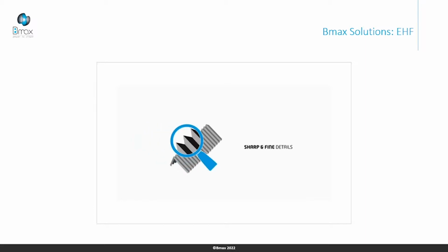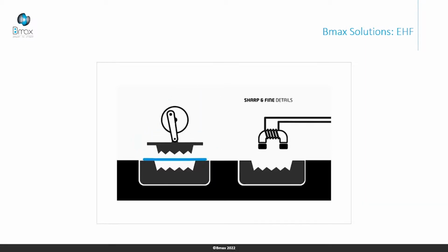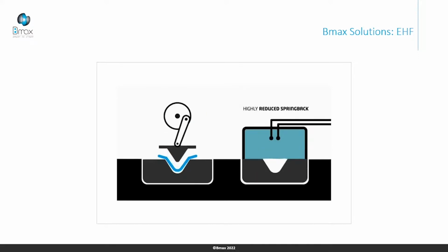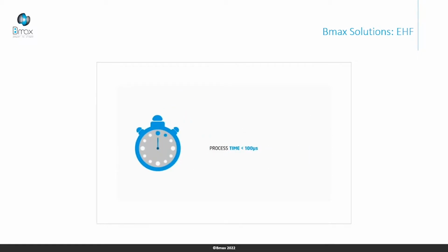We create impact and we can engrave or create new texturing. And we create a new stress through the thickness to change the stress distribution in the blank, and in this way we can change the nature of the springback. All is done in 100 microseconds.